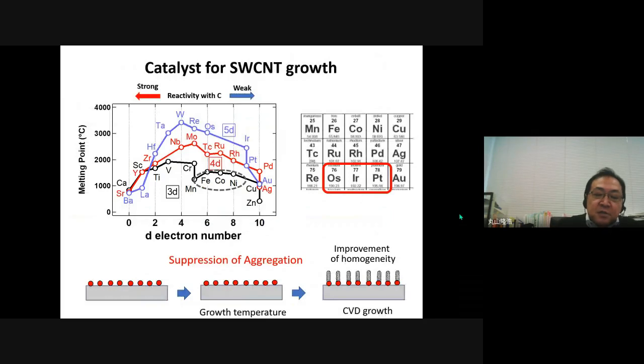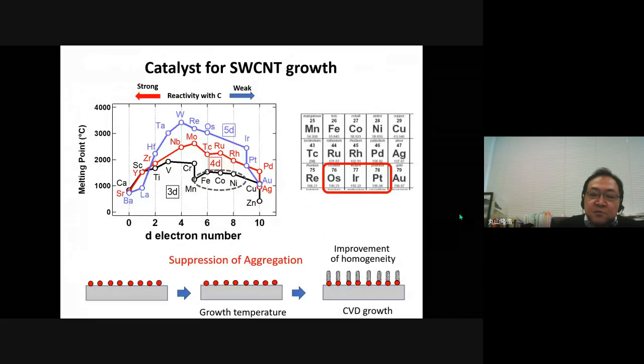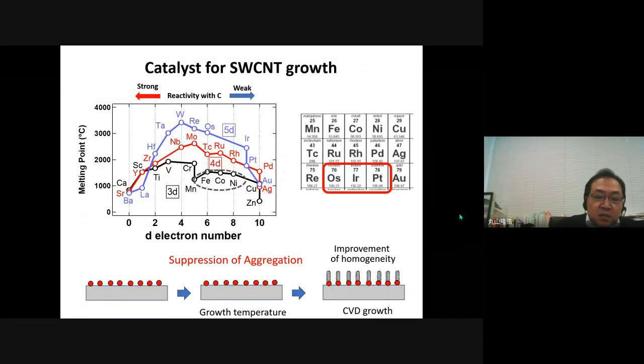To suppress the aggregation, we focused on platinum group metal catalysts. They have 6 to 9 d electrons and show activity suitable for carbon nanotube growth. In addition, their melting points are near or higher than 2000 degrees C and much higher than those of iron group elements. So the aggregation of catalyst particles would be suppressed.